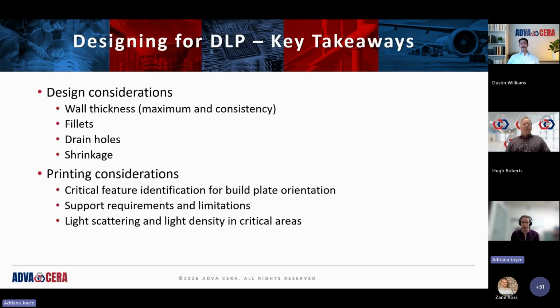We also have to take into account that shrinkage and make sure that if we are aligning features to the pixel grid, the scaled part is what actually aligns. As we're printing, spend a lot of time looking at critical features and faces so that we can orient well on the build plate, both to maximize efficiency and protect the critical features. That also allows us to minimize the number of supports required and consider what overhangs and other features require the supports, minimize those where we can. We also have to look at the light scattering and the light density in the critical areas. That's more of a CAD model and a design, but also impacts the print orientation as we're going through it. I think that's all I've got from a technical perspective.